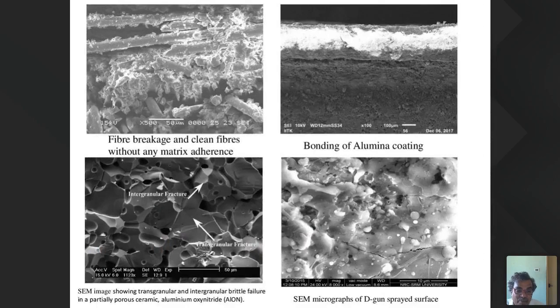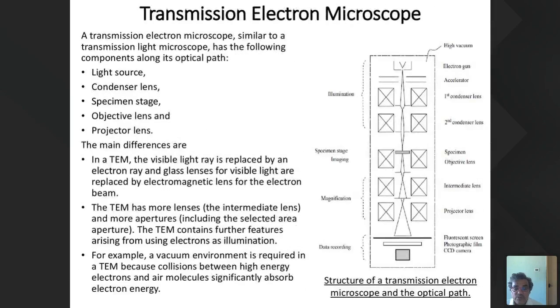So these are all the fiber breakage and clean surfaces. This is my study, when we studied the drilling of high fiber volume GFRP. This is my students' work, where you want to coat alumina coating through detonation gun spraying. See how the adherence between the coating and the substrate is, and what cracks are present when the parameters are not good. All these things you can study.